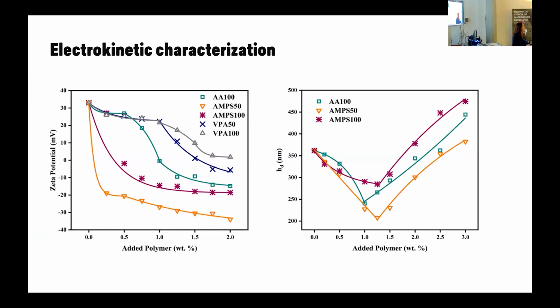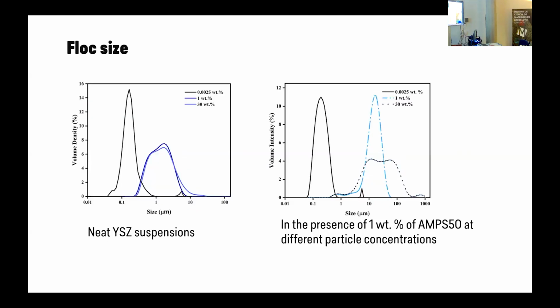We also track the potential of those polymers to lower the zeta potential, right? Because you get more stability if you introduce more charge onto your system. And then we also track the hydrodynamic radius to see where we have access to the most adsorption, or the most stable structure and such. And we track the flock size as well, right? Because we really need to know the capacity of our polymer to bring those particles together. And you observe this through the formation of the flocks.